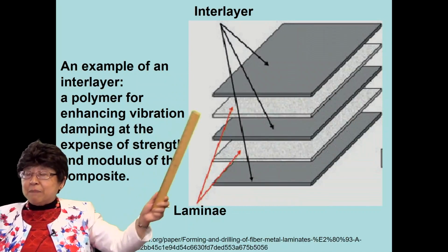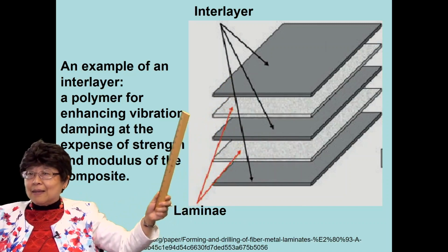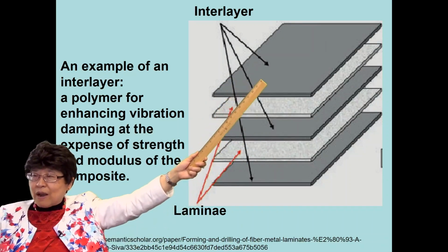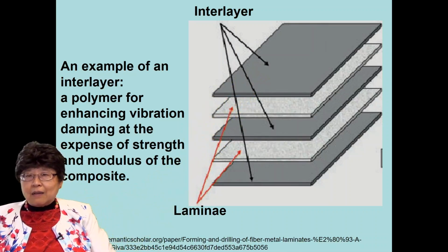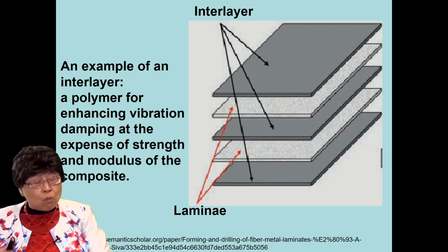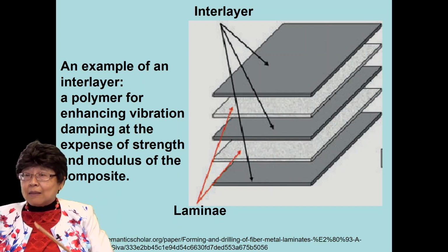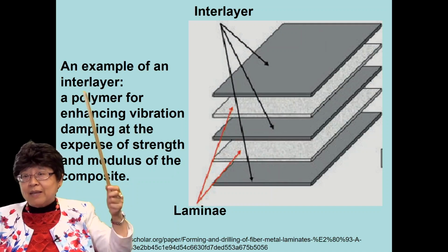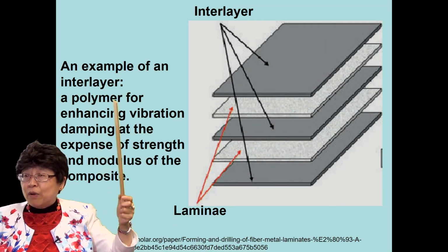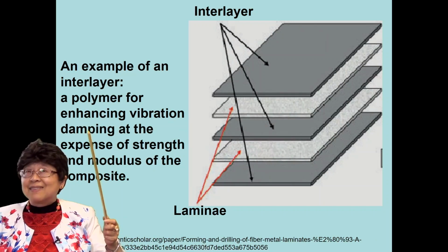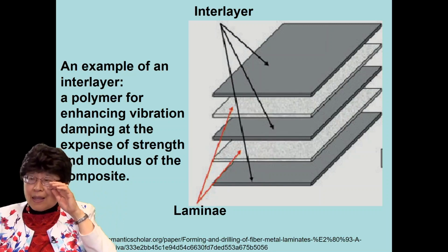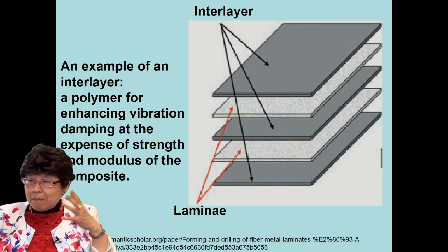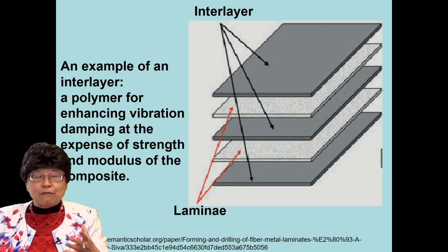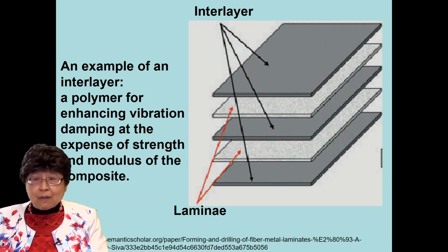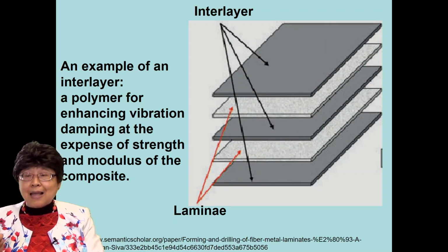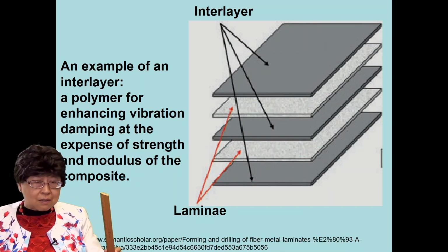Now, the stuff in between the carbon fiber laminae is called an interlayer, in gray here. The nanofiller is actually only one of the types of interlayer. Actually, one of the most common interlayers is a polymer that is put in for enhancing the vibration damping. Like rubber, the polymer akin to rubber, by being an interlayer, would make the overall composite able to have more viscoelastic character. However, this improvement in the viscoelasticity is at the expense of the strength and modulus of the composite.